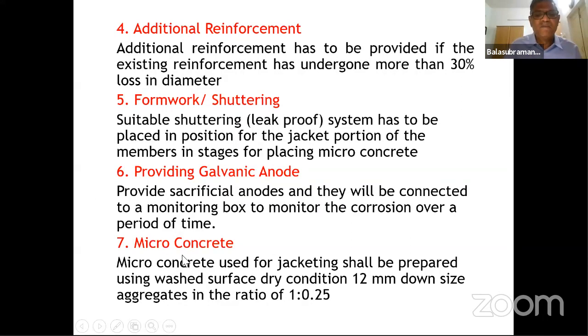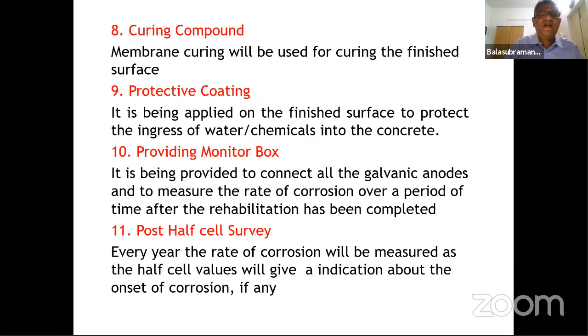Why the cost is going up is microconcrete, because with normal concrete, if the thickness is about 40 mm, 50 mm, it's very difficult to place. So we go for microconcrete. 1 cubic meter of regular concrete is 4,500. 1 cubic meter of microconcrete, with 50% chips, is approximately 50,000. So that's why all these repair values go up like anything. Then we need to give a curing compound, because these are all marine structures. Curing may be difficult. Then we give a protective coating.